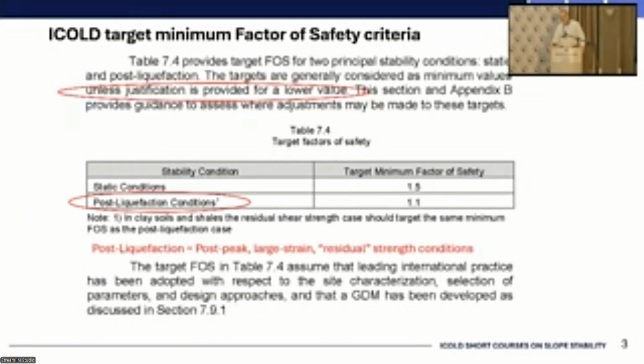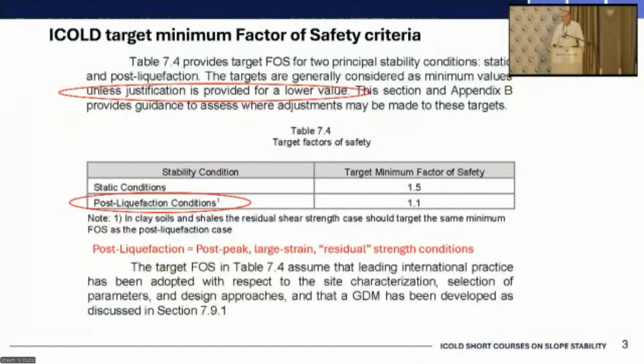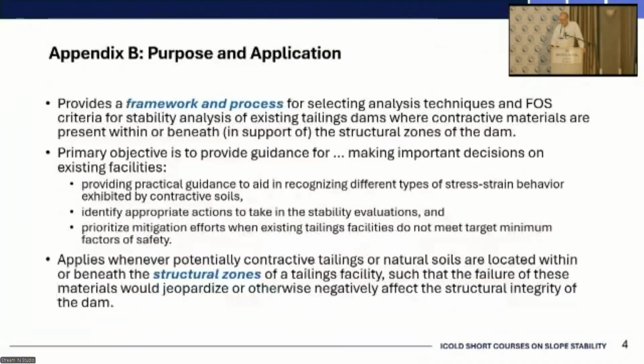I tend to prefer the large strain terminology that Andy prefers as well. It worries me sometimes though, so be careful about that, because as you saw in that stress-strain curve from Brumagino, you can actually have residual strength at small strains if you have a highly brittle material. So you should use this with caution and not get too caught up with the terminology. I often call this the post-peak large strain, residual, post-liquefaction. So I use all the terms just to cover everything.